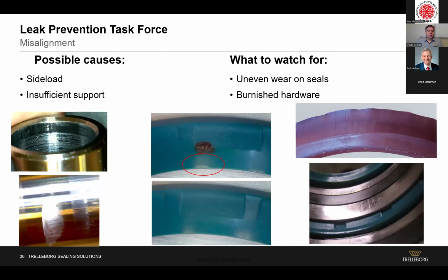And then I mentioned misalignment, but if you have too much misalignment, you can have metal-to-metal contact, and that's obviously going to create metallic particles in the system that can cause damage to the seals. But misalignment can also cause uneven wear on the seals, where on one side you might have heavy wear and on the other side you may not even have contact with the seal. So it's important to make sure the seal is aligned, and that's where having good wear rings and good bearings in the system can help ensure alignment, so you don't have metal-to-metal contact or uneven wear on the seals.